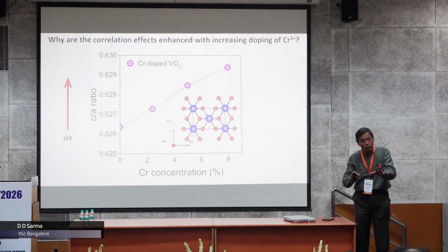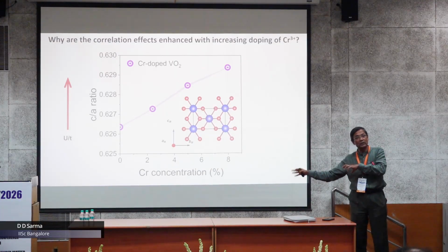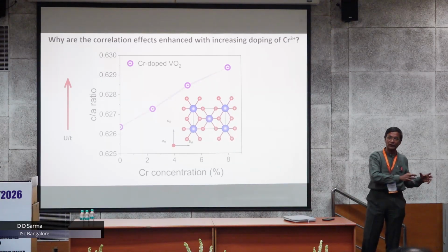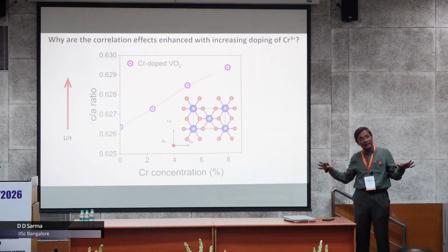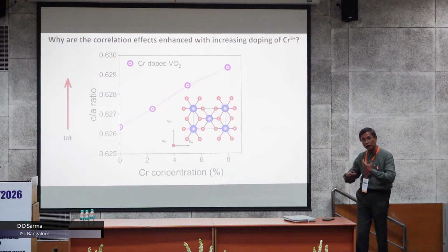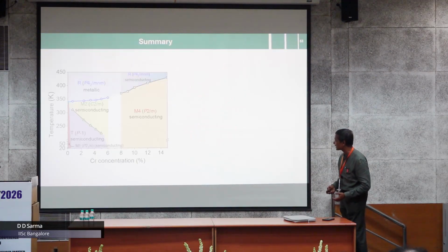So it is exactly VO2 physics, and we have enough spectroscopic signature to prove that chromium 3+ exactly the same number gets captured by vanadium 4+ to convert itself to vanadium 5+. So you're left with VO2, vanadium 4+, with some disorder. So disorder also impacts the ability to remain metallic, but the correlation in fact increases, giving rise to this change.